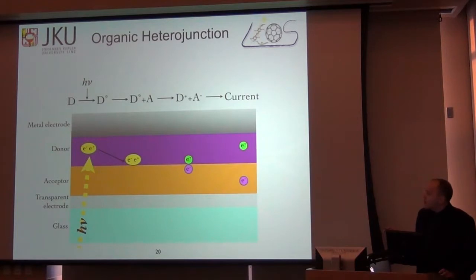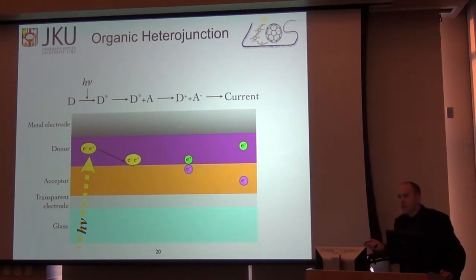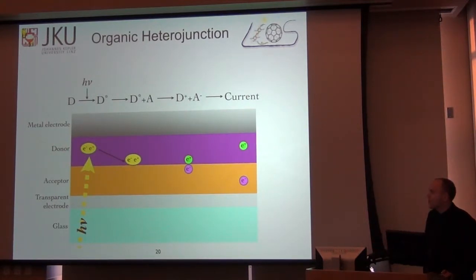So aside from the energy loss, we have one consideration to take into account. We shine light and we generate an exciton in the bulk of the semiconductor. That exciton has to diffuse randomly to an interface before it can dissociate. And that diffusion length is less than 10 nanometers. There's some debate about exactly how big it is in each material, but we can assume 10 nanometers is about the upper limit for the most part.